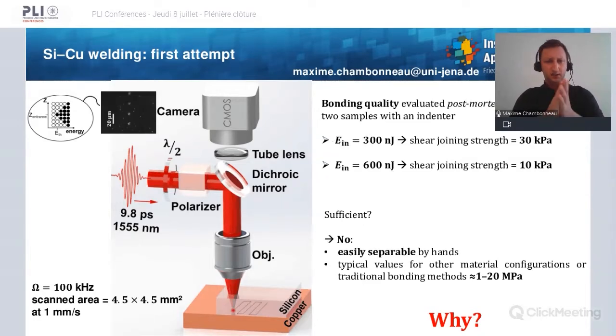Okay, so let's try. If we set the energy to 300 nanojoules, then one can measure a shear joining strength of 30 kilopascal. And then what if we double the energy? Well, then the shear joining strength is 10 kilopascal, which is a surprising behavior, right? By increasing the energy, you would expect a better welding. But the main question here is: is that sufficient? And sadly, the answer is no, as the samples in this case are easily separable by hand, and moreover, the typical values for other material configurations or traditional bonding methods are on the order of 1 to 20 megapascal.